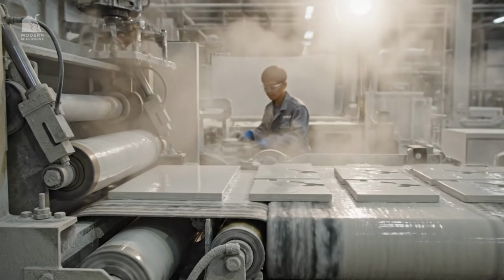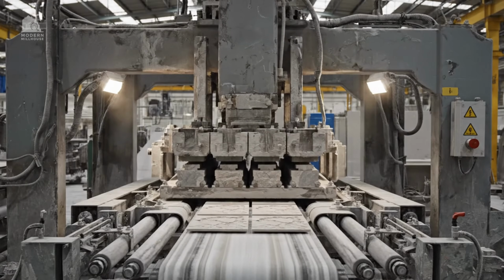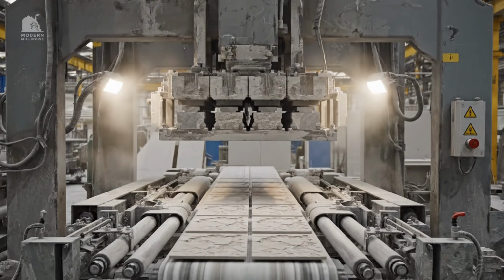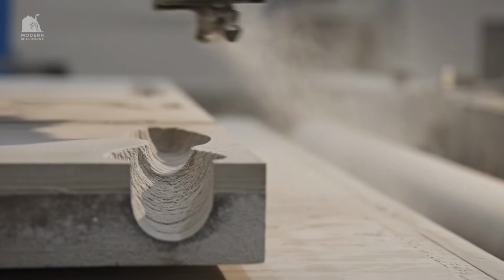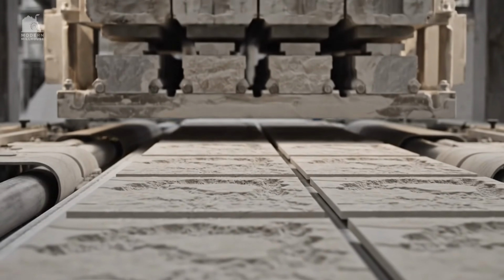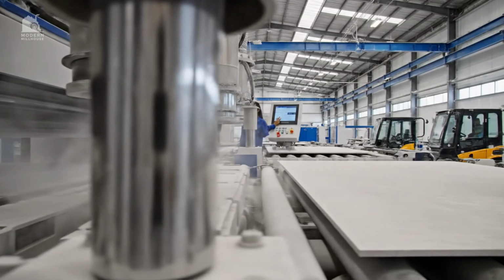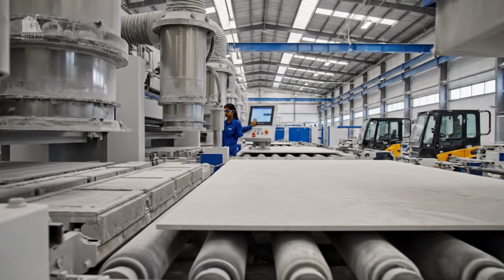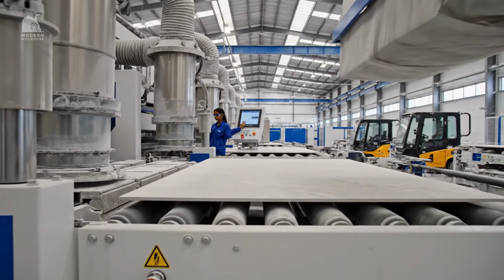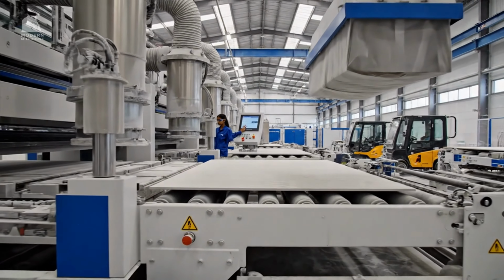Molds are precision tools, and they wear. Edges can become rounded, patterns can lose detail, and thickness can drift if tooling is not maintained. For large format tiles, even small thickness variations can cause bending during firing, so presses are calibrated constantly.